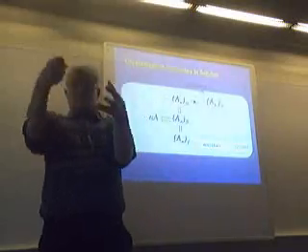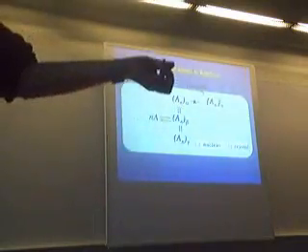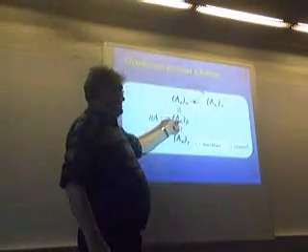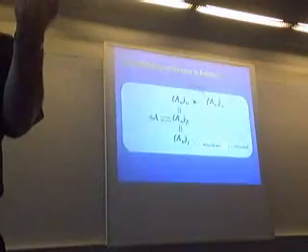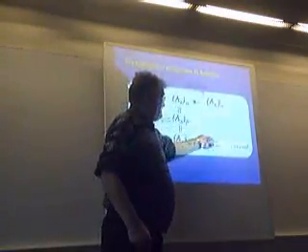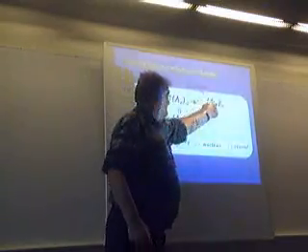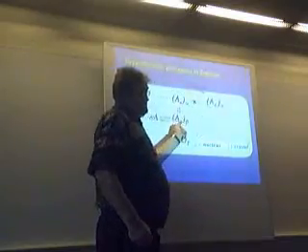Because if I have a molecule which has to be incorporated in that particular cluster, this cluster cannot cross the critical size. It will prefer to decompose back into smaller clusters, and therefore in this way I can ask myself whether I can give a chance to the second polymorph to grow. Because if I select this inhibitor properly, since I know the structures of the various polymorphs, I can select an inhibitor such that it will interfere with the formation of this, but will not interfere with this particular second polymorph.